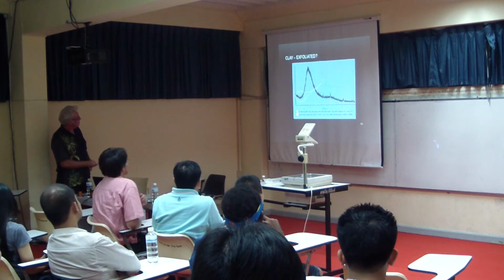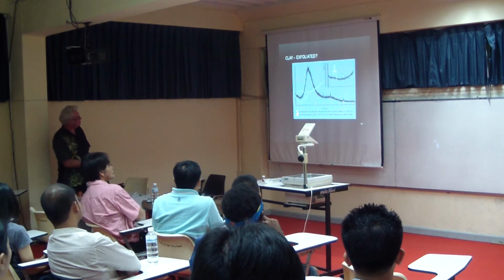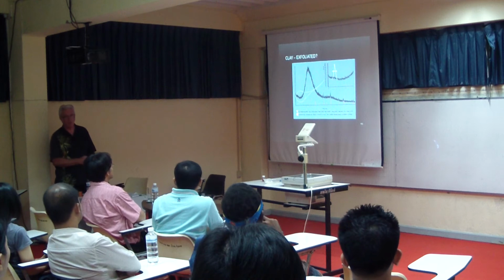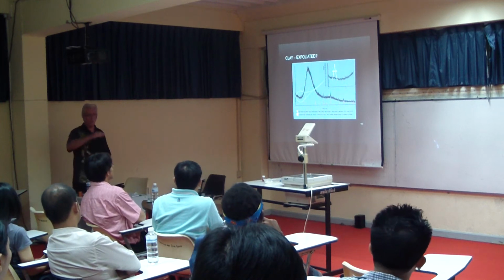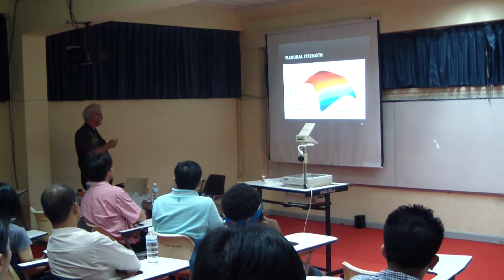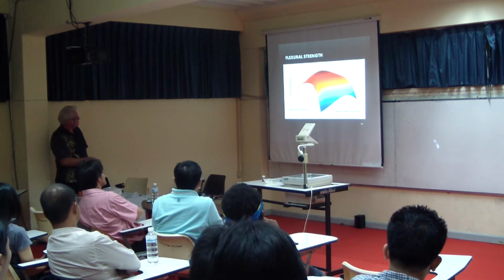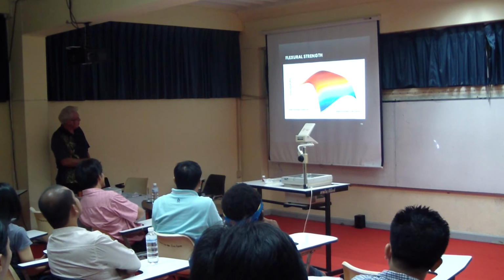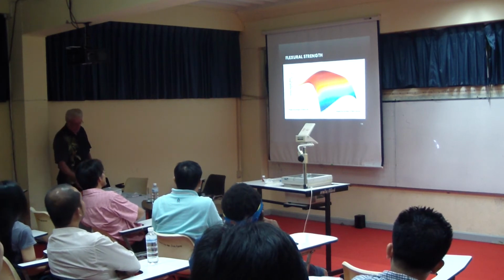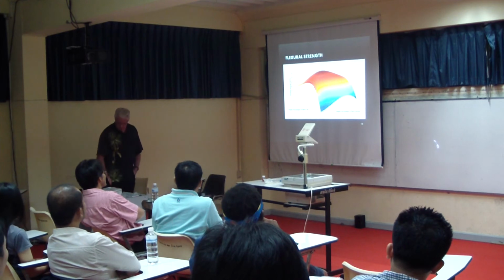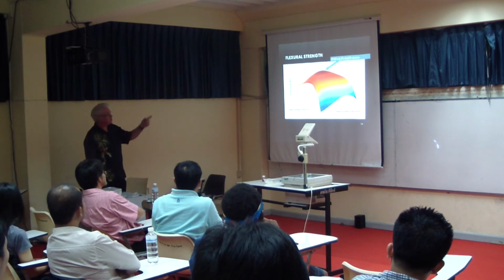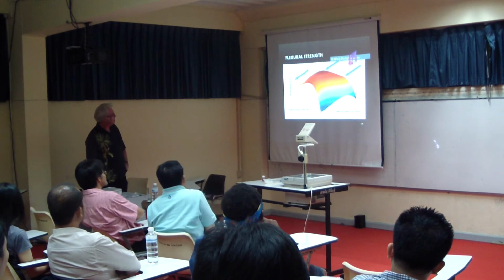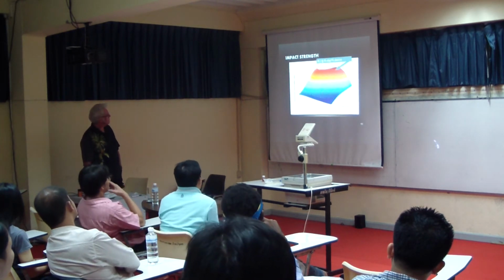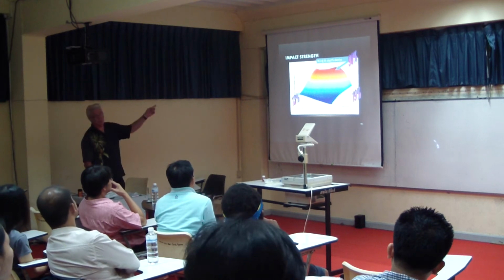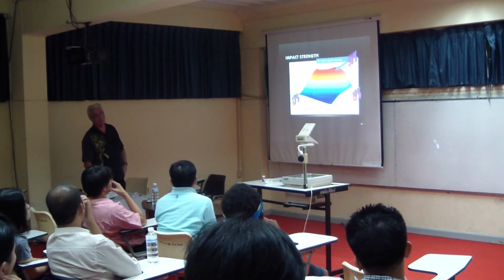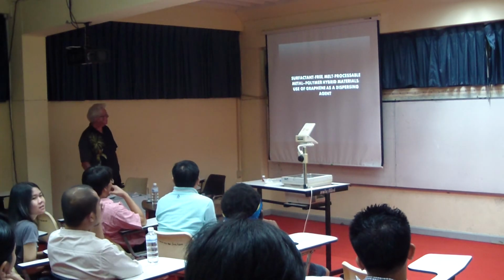And we did some work. We exfoliated it because there really should be an X-ray diffraction peak there that was missing. So we know that we didn't have this layered structure. And you can see here, we added two different sorts of particles, nano alumina and nano clay, and we've got some interesting properties. By joining the two together, we've got much better properties. We don't need to go through more. You can see there that strength went up, and also the impact strength.